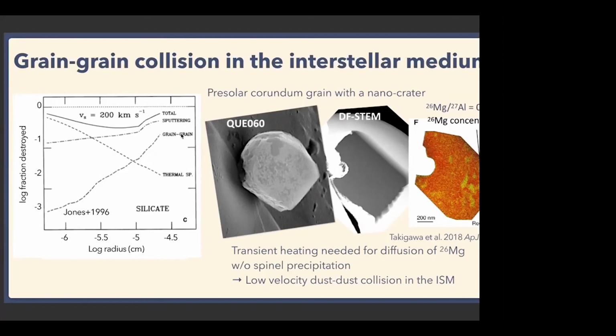But we have one good example, probably indicating that a grain had experienced grain-grain collision. This grain is a presolar grain. This is the same grain I showed before. This grain was formed by direct condensation from the gas. But if we made a thin section, a very thin film from this grain, and observed it in the TEM, we can see the interior structures, and we found that there is a cavity here. This grain has a nano-sized nano crater.